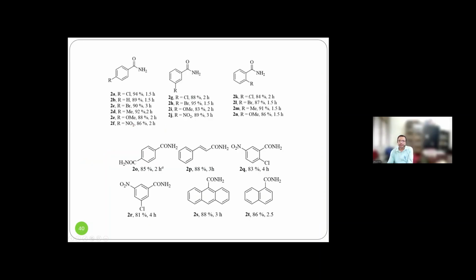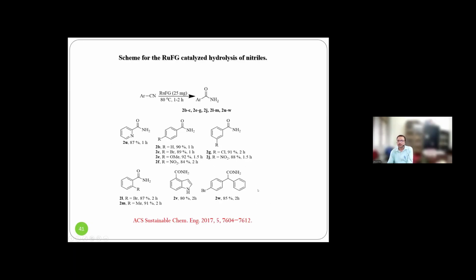We tested the reaction in the presence of electron withdrawing, electron donating groups, halogens, and everything, polyaromatic compounds. Then we tried this reaction with acetonitrile, cyanide to amide, and we were also successful in the preparation of cyanide to amide. Various amide derivatives we synthesized.